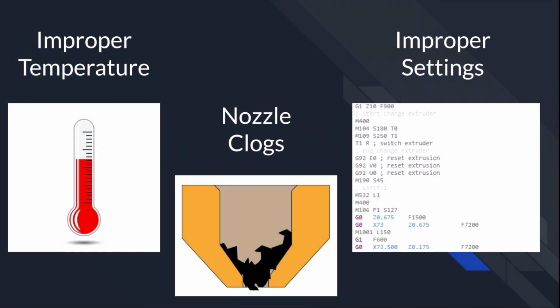If your printer is not extruding filament, one of the causes could be an improper print temperature. So you could be printing too low, and you'll have to increase it in order for the filament to heat to its proper temperature, thus get softer and melt and be able to extrude. Another cause could be a nozzle clog. So filament literally just gets stuck inside of it. So you're going to either want to purge the material or do a cold pull. And the last one, while not as likely, has actually happened to me, is having improper settings. So there could be some communication issue between the slicer and the printer, and it's not sending the proper instructions that's needed.